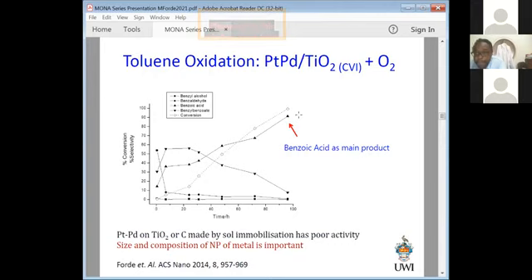So the major product here would have been the benzoic acid. So it's different. And of course, at that point, the catalysis person says, oh, I need to find out what's happening with the surface. If I know how these particles are arranged on the surface, I'll understand how to do this reaction. Why is the platinum-palladium working on titanium, but if I put it on carbon, it doesn't work very well? It turns out that the size and the composition is important, which I'll show you shortly.